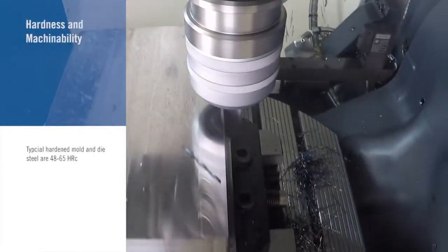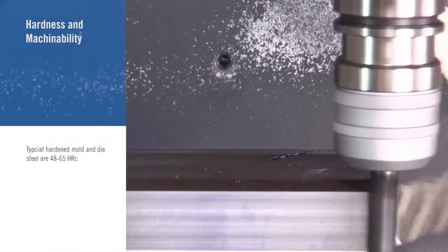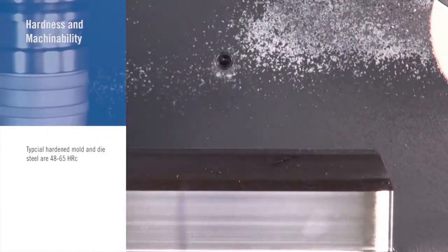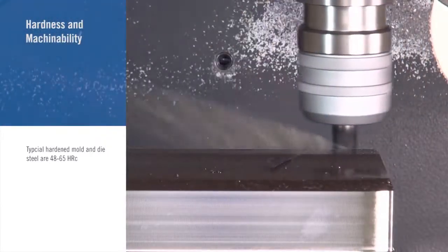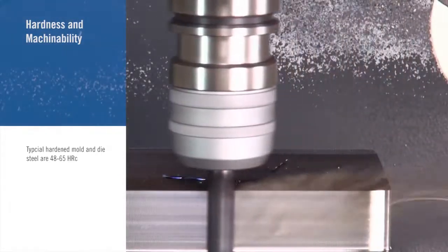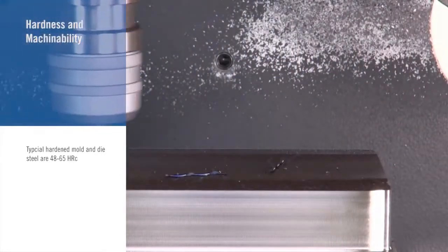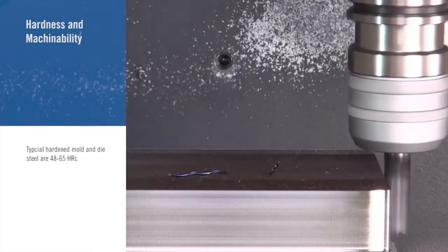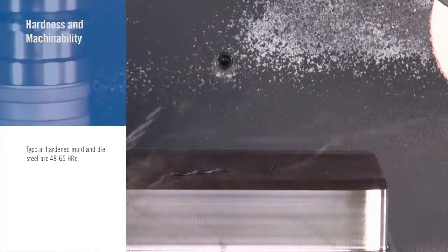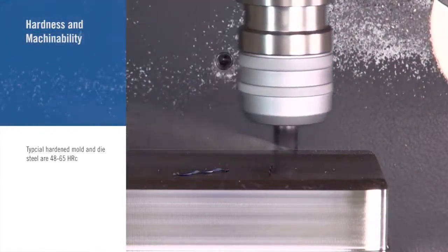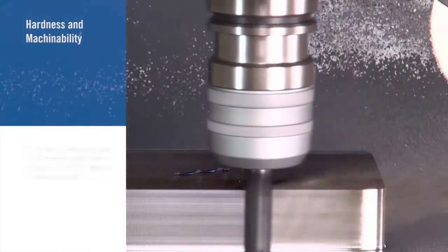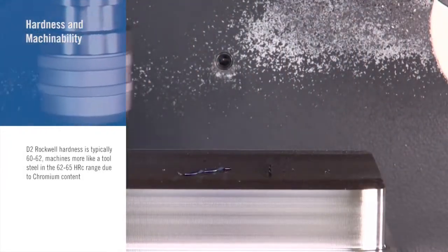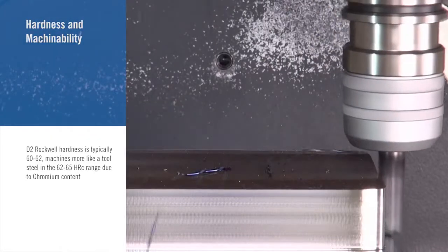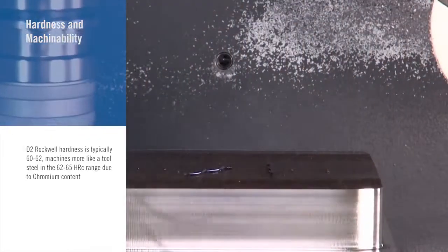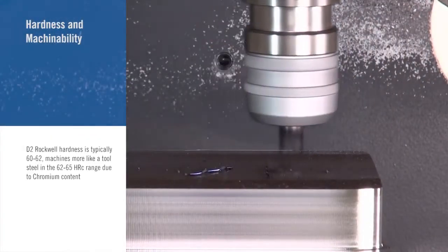Now, a typical hardened tool steel is roughly 48 to 65 Rockwell, and that's just looking at the end mill side of things. If you look at an inserted application, there's probably more in the 35 Rockwell, maybe low 40s is considered hard, but just for the end mills, it's about 48 to 65 Rockwell. Now, you do have to keep in consideration the material you're machining. Not all hardened tool steels are the same. For example, D2 is about 60 to 62 Rockwell typically, but because of the chromium content, you actually need to treat that material like it's 62 to 65 Rockwell.